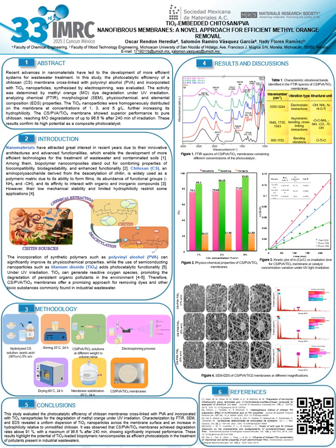Under UV irradiation, titanium dioxide generates electron-hole pairs capable of producing reactive oxygen species (ROS), such as hydroxyl radicals, which effectively degrade organic contaminants. Our goal was to develop a chitosan PVA nanofibrous membrane embedded with titanium dioxide nanoparticles using electrospinning, and to evaluate their photocatalytic performance in degrading methyl orange from aqueous solution under UV irradiation.